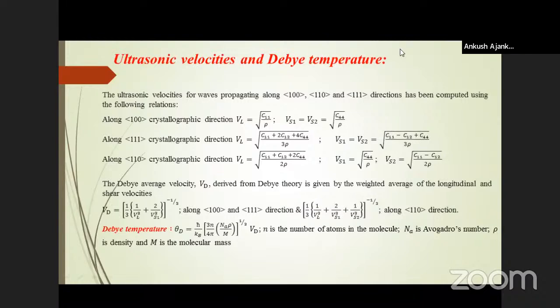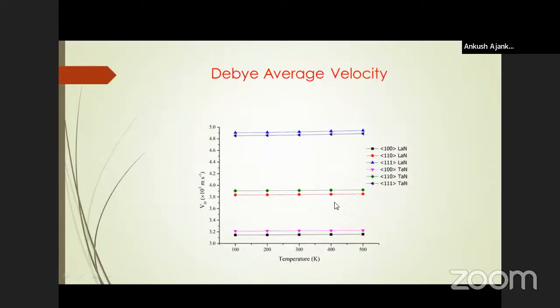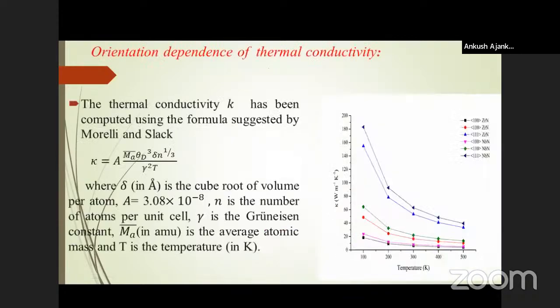In this slide, the formulation related to the ultrasonic velocities for the longitudinal wave and shear mode has been given. Debye average velocity Vd has been computed with the values of VL and VS with the help of these relations in the 100 and 111 directions, while in the 110 direction, the formula for Debye average velocity is this. Debye temperature has been evaluated using this expression. The plot of Debye average velocity has been shown in this figure. The thermal conductivity has been evaluated using the formula suggested by Morelli and Slack, and the plot of thermal conductivity has been shown in this figure.